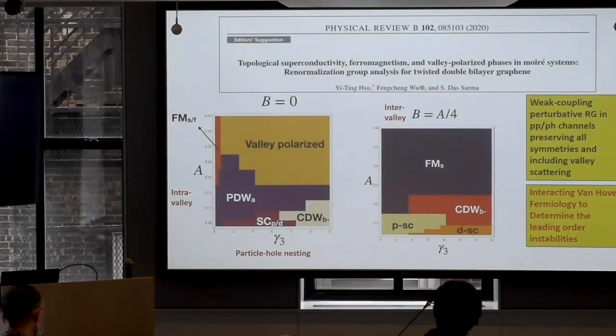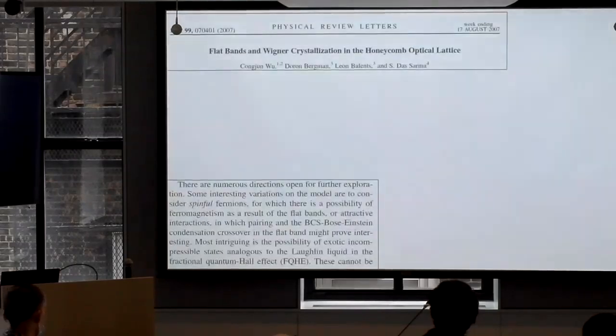But I do not think that these findings of ours, and there are many, many papers like this in the literature, they're all very nice theoretical papers. But I think TC for all these superconductivity is very, very low. And I do not believe the superconductivity that is observed in any of the graphene samples has anything to do with these RG calculations. This is a strong statement, but among experts, I do not want to be wishy-washy. That doesn't help. If I say it could be this, that could be that, well, then at my age, that makes no sense. I'm going to take stands, okay?